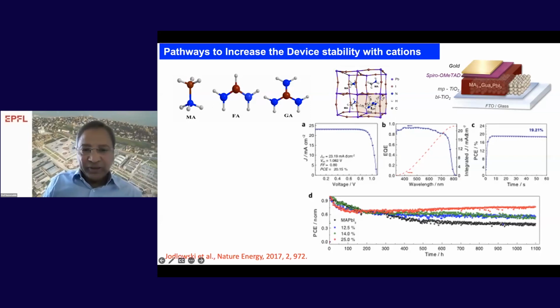That's a take-home message. Now, how about the efficiency? At that time, the efficiency was around 20%. However, if you look at the stability curve, the black line shows 1000 hours of stability under light and heat conditions, decreasing significantly compared to the cation containing 25% guanidinium. So the guanidinium-containing cation shows significantly enhanced stability. This is how cation modification enhances the stability of perovskite solar cells.